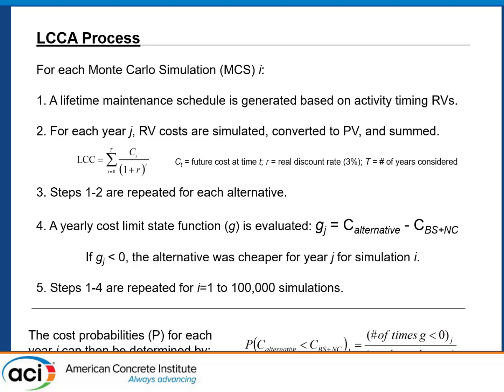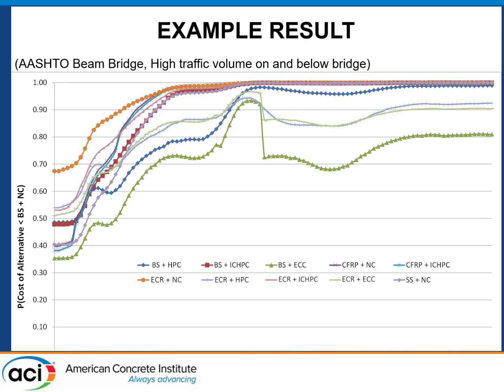And we repeat these steps 1 through 4 for about 100,000 simulations, and that gives us enough data to compute the probabilities that the alternative was less than the baseline. We did this for a number of scenarios. I'll show you one here as an example. This is for an AASHTO beam bridge, high traffic volume on and below the bridge.